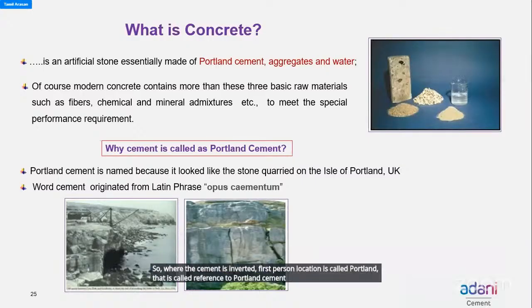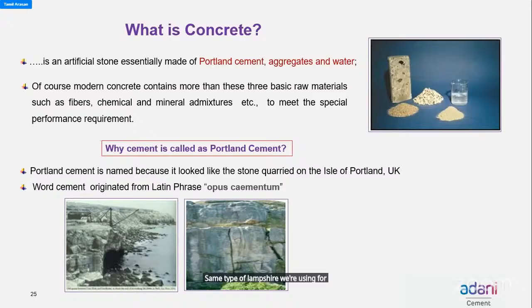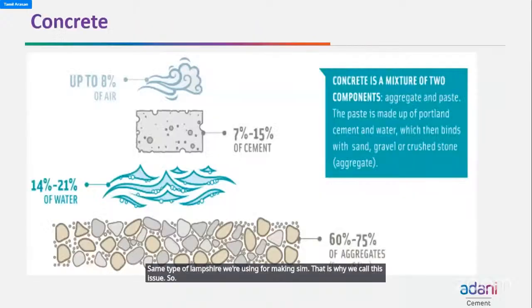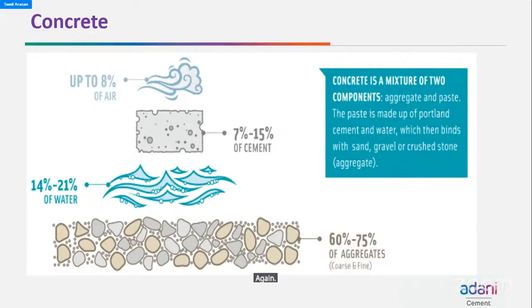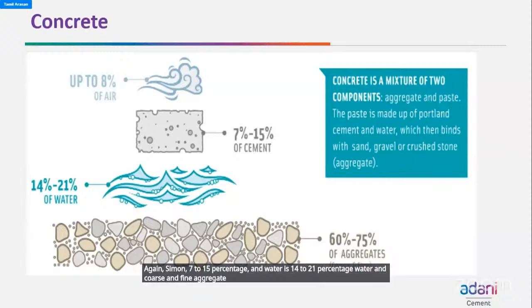We make cement from the same type of limestone that we have in India. That is the reason we call it ordinary Portland cement or Portland slag cement, whatever we use, based on that same type of limestone used for making cement. Without air we cannot make any concrete. From 2 to 8% air must be there in the concrete. Cement is 7 to 15%, water is 14 to 21%, and coarse and fine aggregate is 60 to 75% overall by volume.